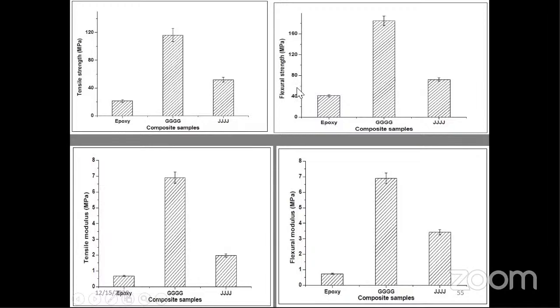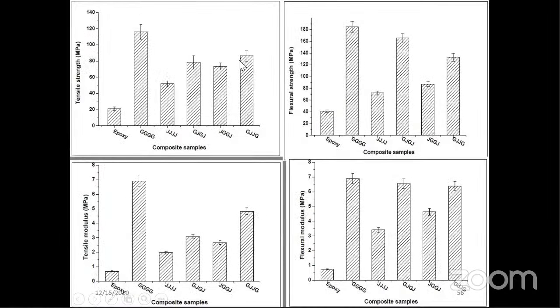flexural strength, flexural modulus, and tensile modulus. All the results are the same. So instead of going for plain composites, the next concept is going for hybrid composites. So addition of a hybrid composite: instead of plain jute material, a combination of glass and jute. Still none of the materials have the capacity to replace the continuous 4-layer glass fiber composites.